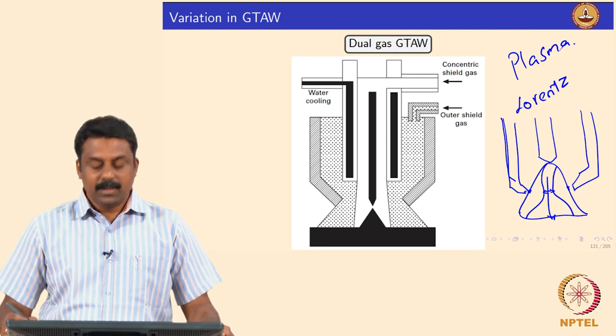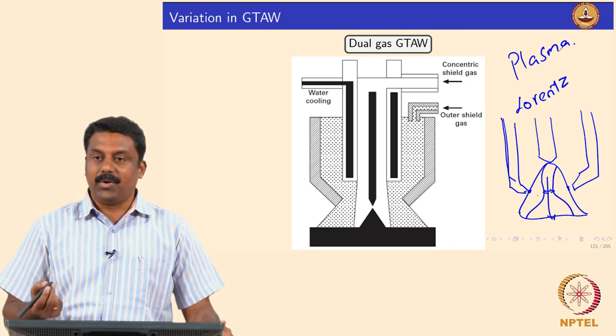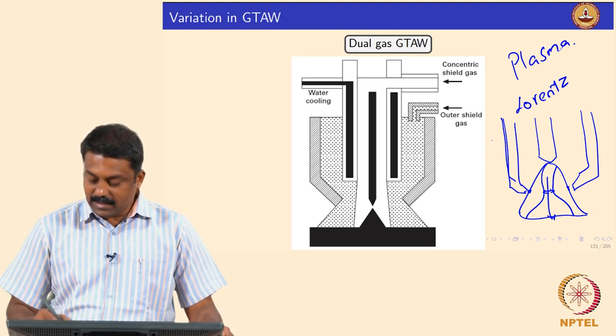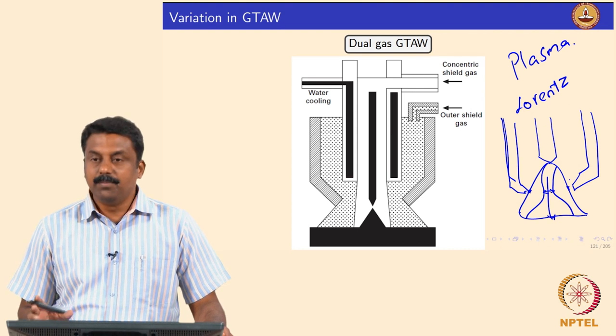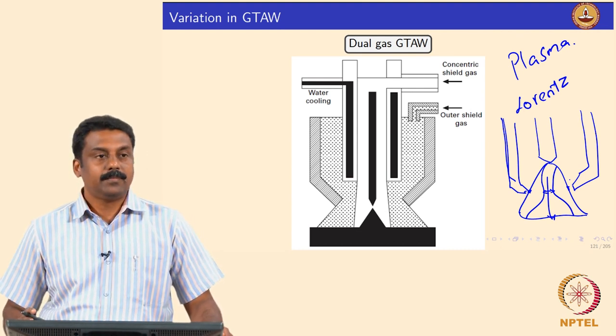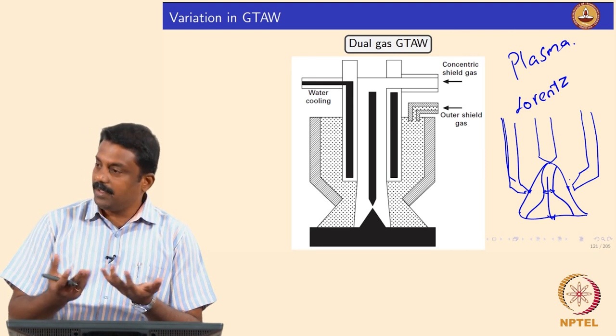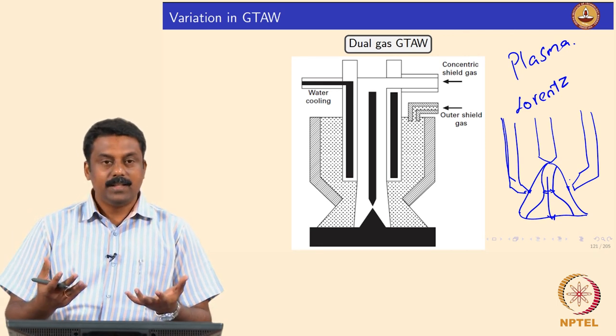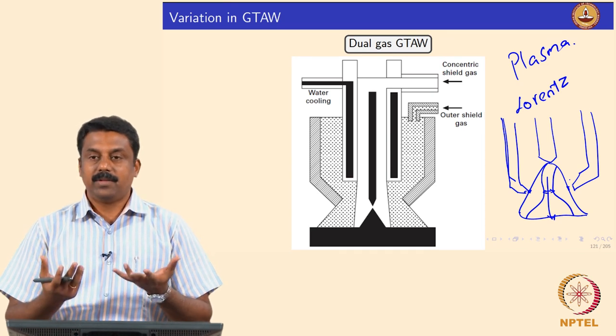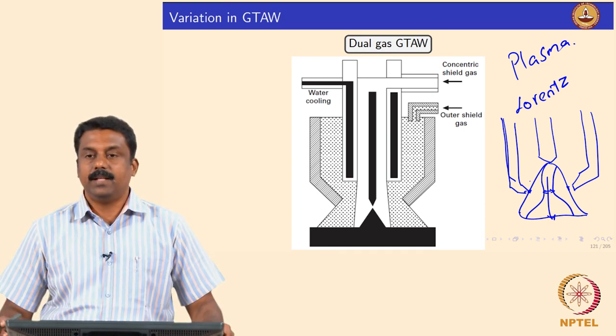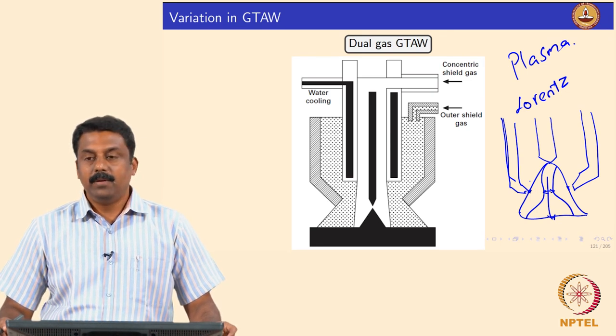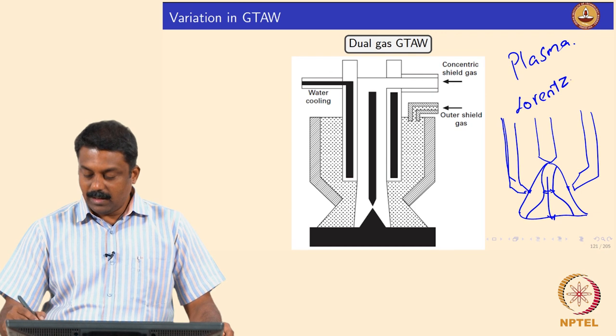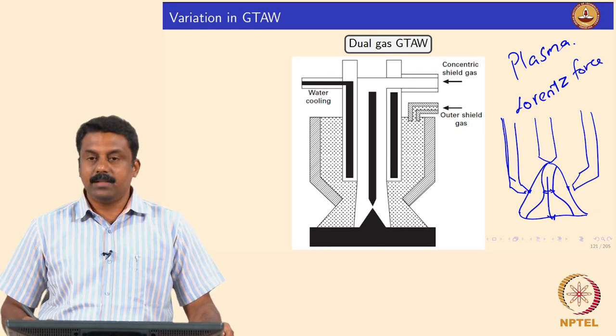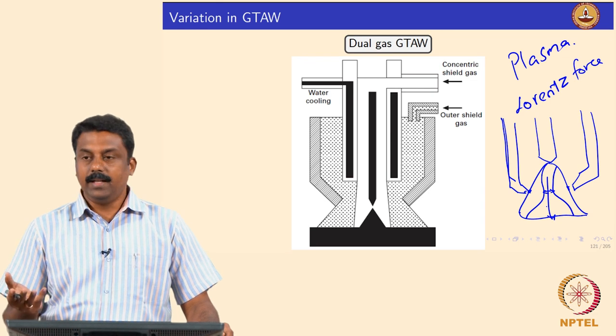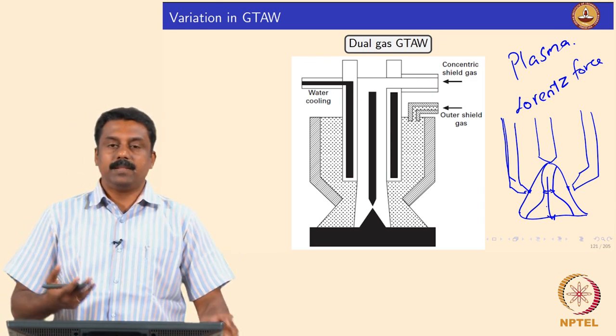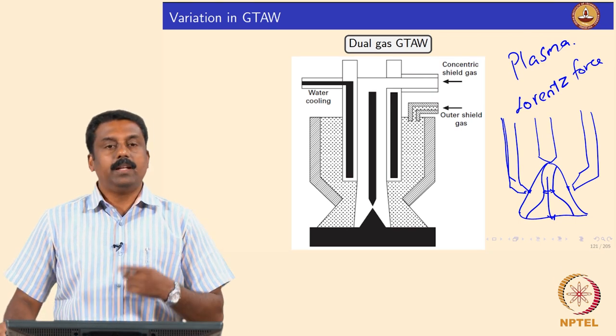Yes, it's clear. So by just doing a simple trick, by cooling an arc using an external shielding gas, we can constrict the movement of the electrons and ions. If you are constricting the movement, obviously they collide with each other, and they generate more ions and more electrons. Then you can reach a state at which the arc plus the plasma is generated, right? By doing so, you create so much Lorentz force that the plasma jet velocity increases tremendously, isn't it? Because you increase the Lorentz force, the plasma jet velocity is also increased.